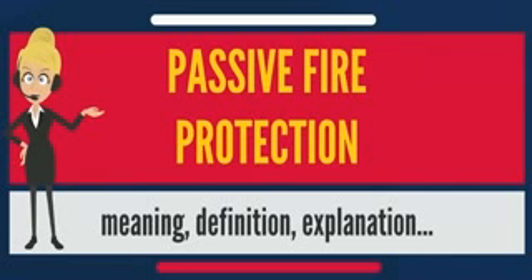Too much water can be a problem, however. Concrete slabs that are too wet will literally explode in a fire, which is why test laboratories insist on measuring water content of concrete and mortar in fire test specimens before running any fire tests. PFP measures can also include intumescents and ablative materials. The point is, however, that whatever the nature of the materials, they on their own bear no rating. They must be organized into systems, which bear a rating when installed in accordance with certification listings or established catalogs, such as DIN 4102 Part 4 or the Canadian National Building Code.